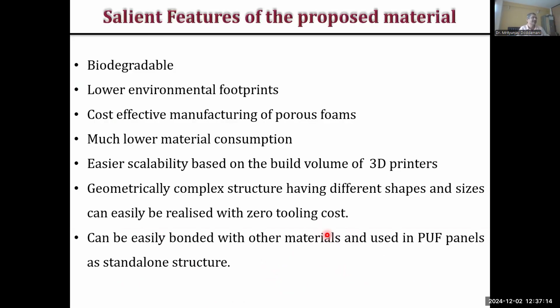And these are the salient features of this proposed material, the research outcome which was funded by ISHRAE. The material is biodegradable. It has a lower environmental footprint, cost-effective manufacturing of porous foams, and the same pellets I can put into injection molding and get that as well. Much lower material consumption because now we have a Kelvin structure. No doubt the Kelvin structure is not possible in an injection molding machine, but because of the Kelvin structure, we are saving a lot of material all around.